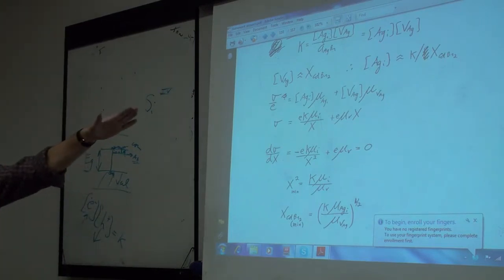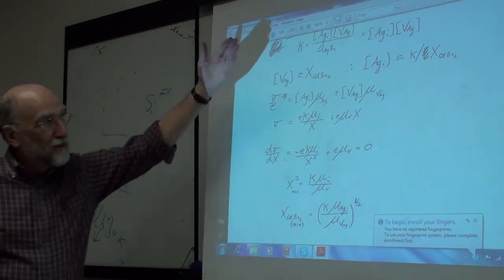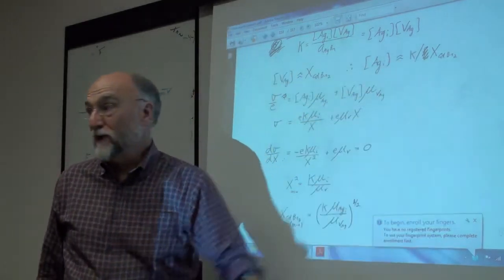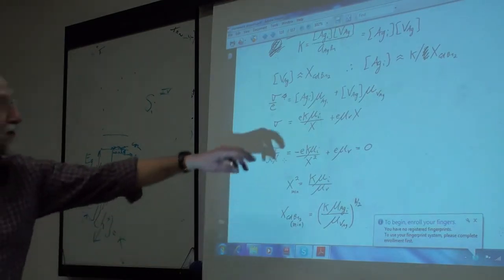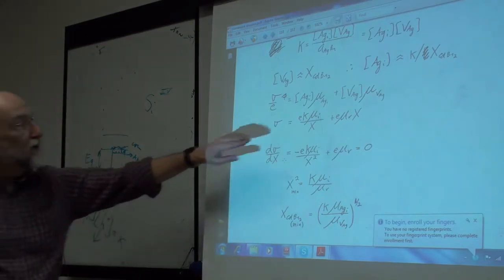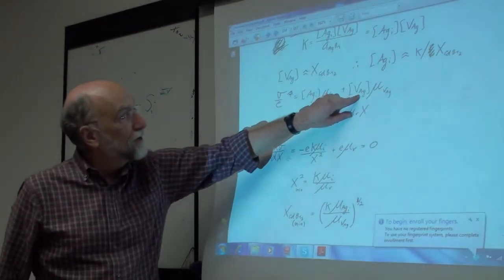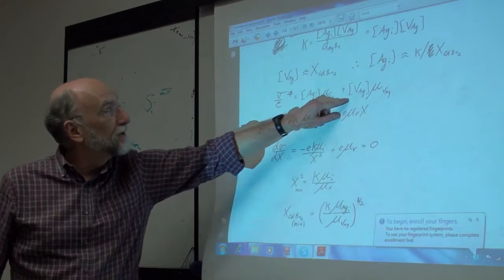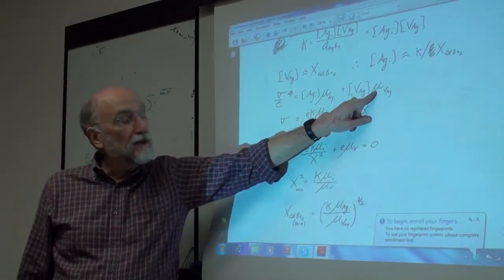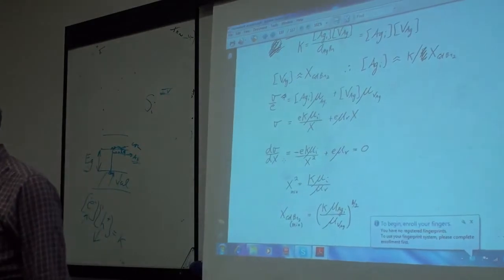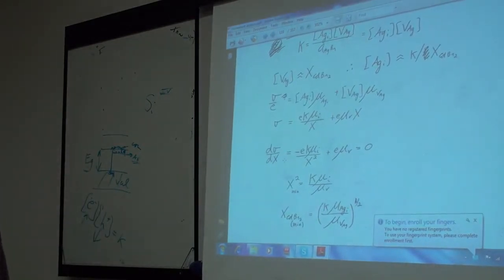The extrinsic conductivity, of course, doesn't, because it's not thermally activated. It just depends upon the amount of dopant you add. In fact, it goes the other way, because once you get into this regime over here, where the vacancies are controlling the whole thing, the concentration of vacancies is constant. It's simply equal to the mole fraction of cadmium bromide, and the mobility can actually, in certain cases, decrease a bit with temperature, or certainly doesn't increase that much.